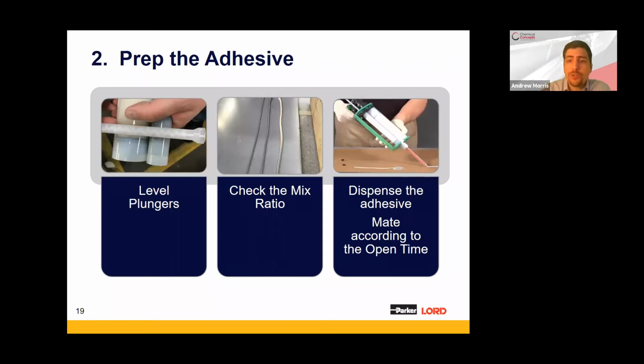If using cartridges, the next step is to prep the adhesive. So the cartridge is inserted into the gun. If you have an adjustable gun, you want to make sure that it is set up for the correct ratio. The Lord 810 is a 2-to-1 ratio product, so you want to keep that in mind if you have that adjustable gun set up. You want to remove the cap and dispense a small amount of adhesive until the adhesive is coming out of both sides.